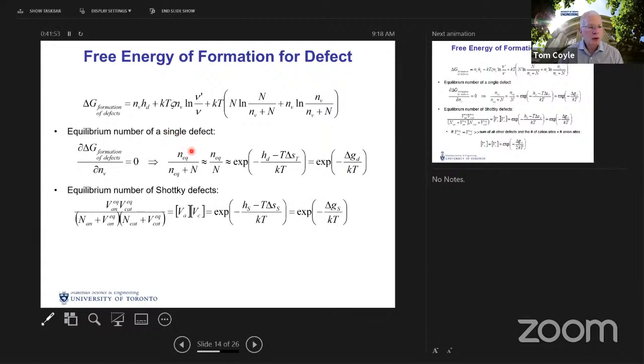So that was for the case of a single defect, which would describe the formation of a vacancy in a metal. A similar approach can be used to generate an expression for the equilibrium number of Schottky defects, but just a bit more complicated because now we have to worry about vacancies on both the anion and cation sites instead of just one type of site. But in the end, it looks pretty much the same.